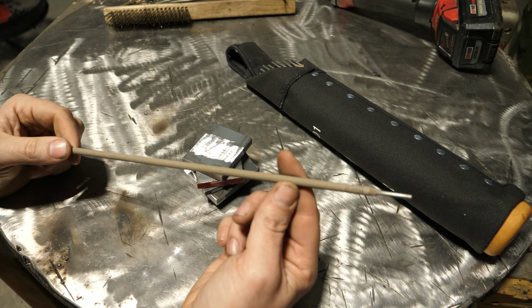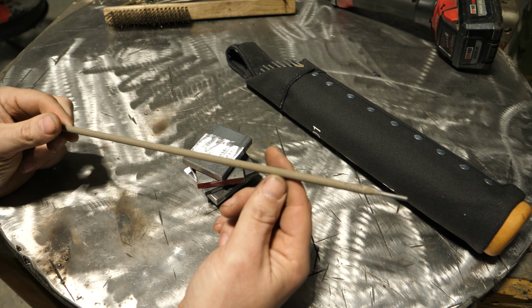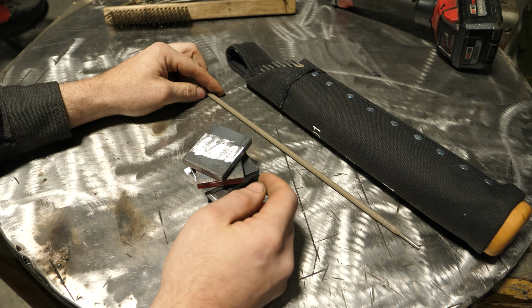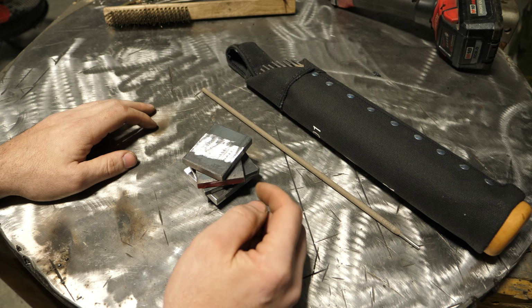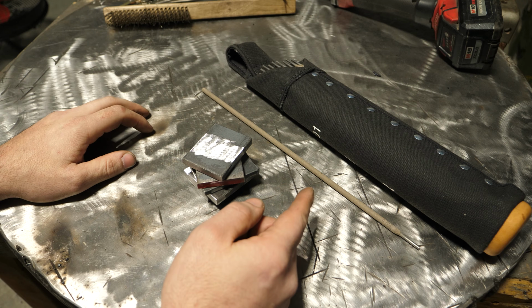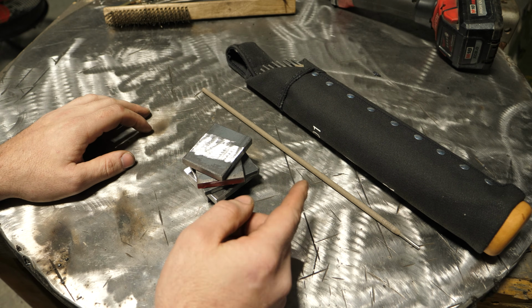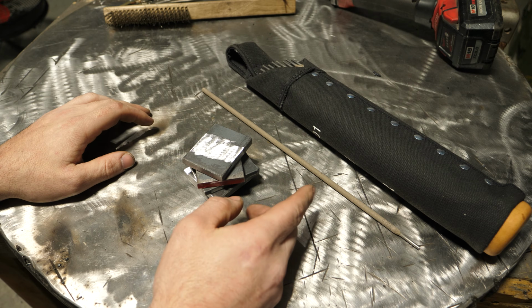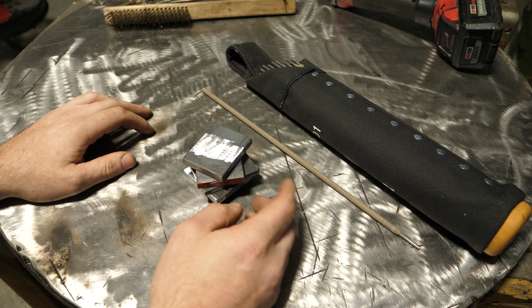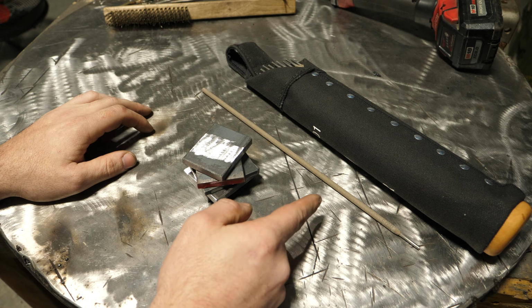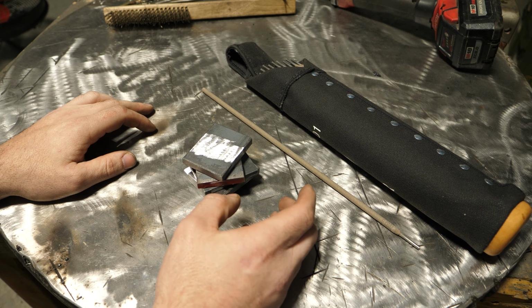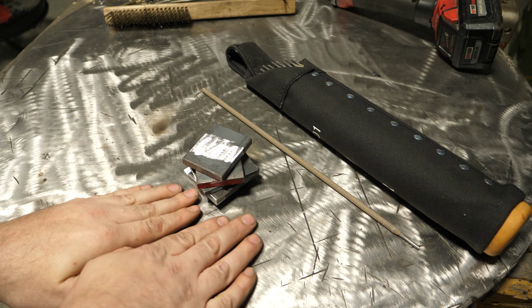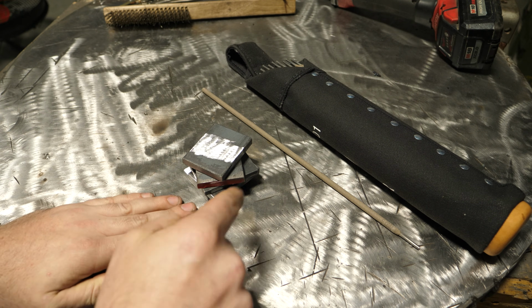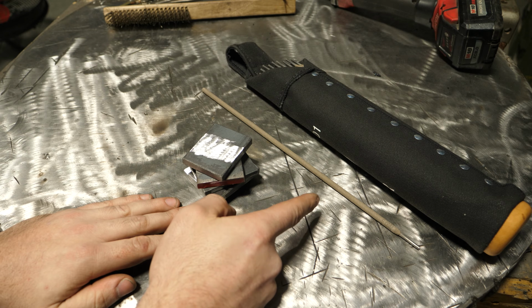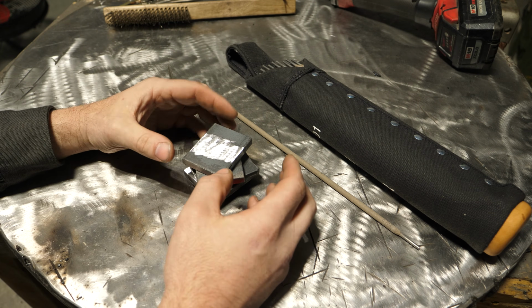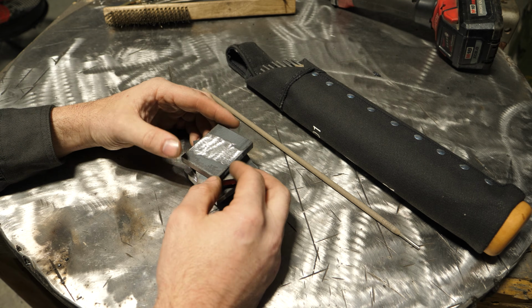But this rod is very, very big for an 1/8" rod because of how much flux is on here. This flux contains iron powder. That iron powder turns into part of the weld deposit, and that's why you get very high travel speeds with this, very high deposition rates, which is kind of why they call it jet rod. You know, get stuff done. Commonly used on trailers, on tanks, or anything like, I don't know, ships where you have a butt weld that you just need to weld down. Great rod for that, especially in bigger than 1/8" sizes. But it produces a very wide weld, very high deposition, like I said.